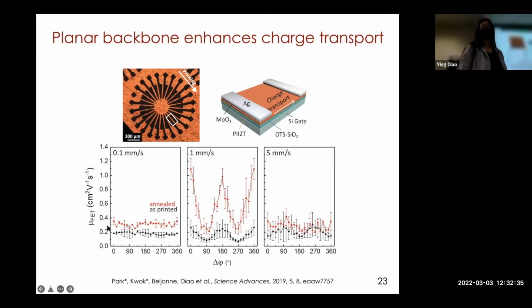And the charge carrier mobility, which is the speed of the charge carrier, remains low. Whereas when we stretch out the polymer, we then preferentially transport along the polymer backbone. So that's these high points along the polymer backbone direction. And also the charge carrier mobility, the speed of the charge carrier, is significantly enhanced by 3 to 4 times. So that's telling us that the planar backbone, although we only planarize by 10 to 20 degrees of the torsion, can drastically enhance the speed of the charge carrier.